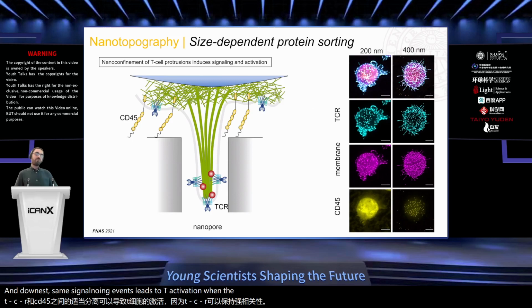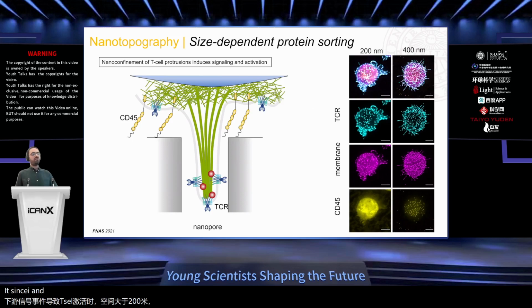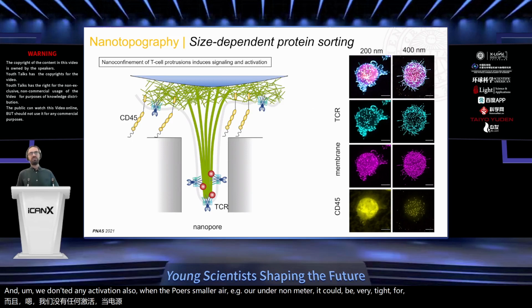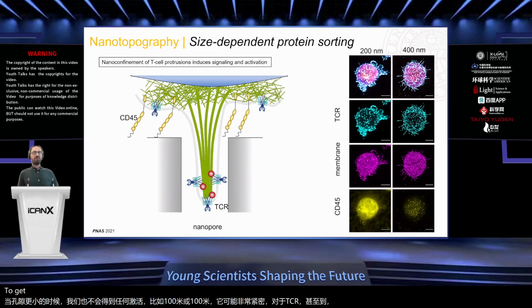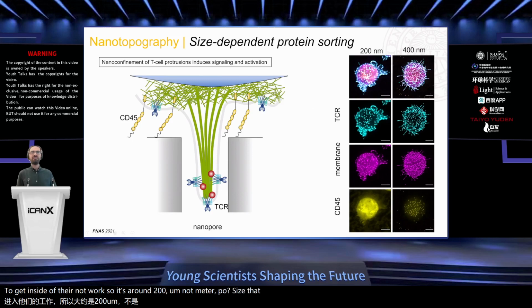When the spaces are larger than 200 nanometers, the TCR and CD45 molecules are not separated anymore inside of the nanopore, and we don't get any activation. Also, when the pores are smaller, for example, around 100 nanometers, it could be very tight for TCR even to get inside of the nanopore. So it's around 200 nanometer pore size that the magic happens.